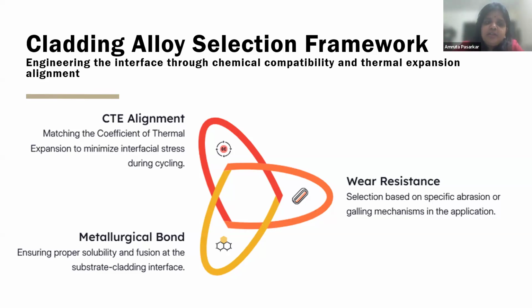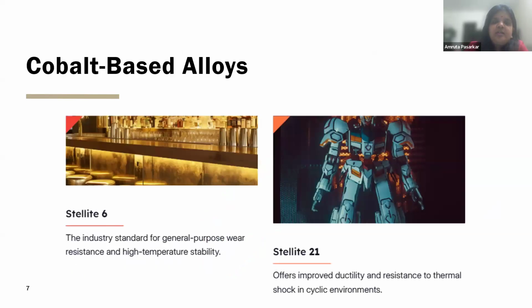Then the metallurgical bond. There should be a very good metallurgical bond between the powder and the base metal. Because if there is no fusion between the two, then it is obviously going to crack, or it is obviously going to break. Then the wear resistance. Selection is based on the specific abrasion and the galling mechanism in the application. There are many types of alloys that can be used, but mostly cobalt-based alloys and nickel-based alloys can be used as the cladding material.